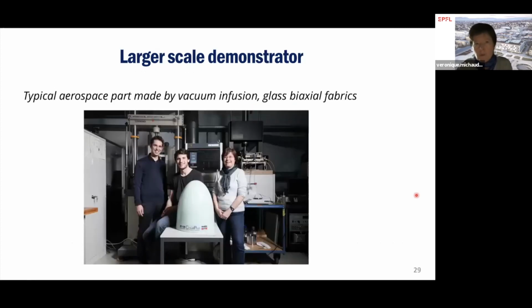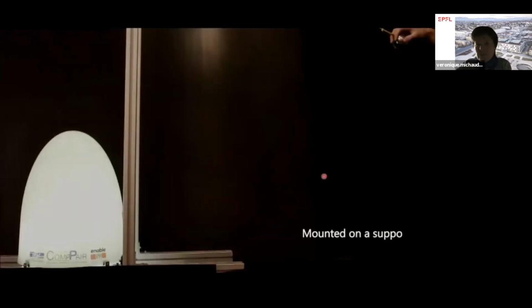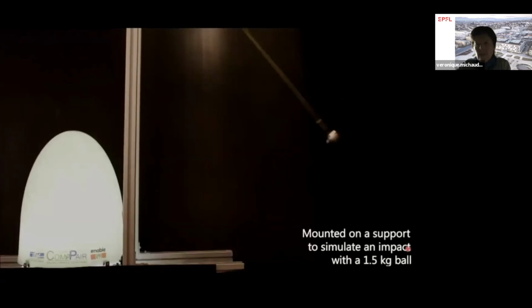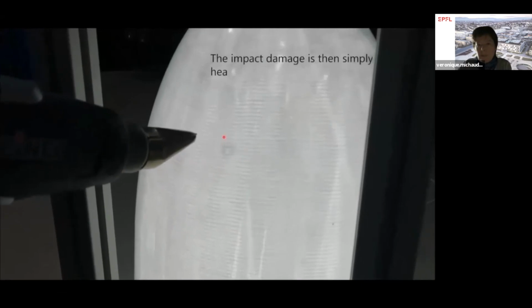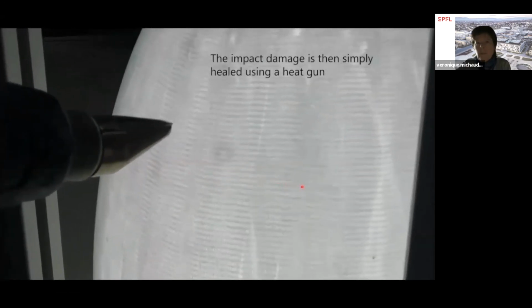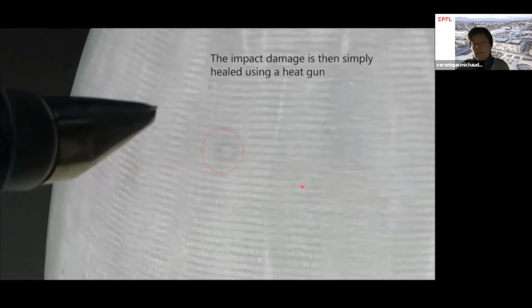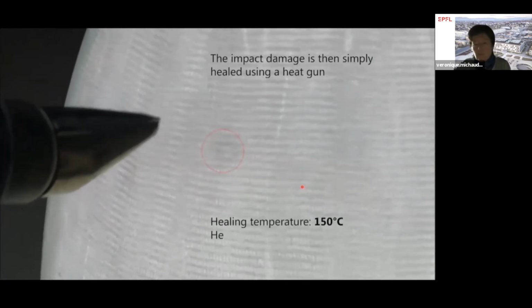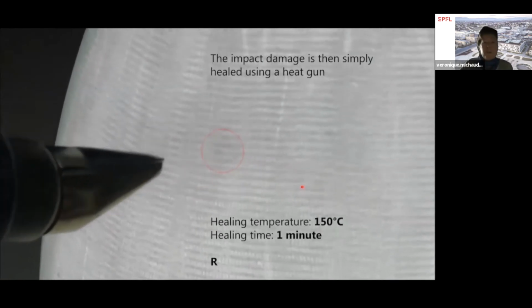So we went on to do larger scale demonstrators. We made a typical aerospace part with the glass biaxial fabrics. We were very happy to be in front of this, beautiful. And then you see that the video here is mounted on a support. We have a 1.5 kilogram ball that is impacting, and we have the impact that we can see here. We use a simple heat gun for 1 minute in this case, and the impact actually disappears under your eyes. So it's actually quite impressive.